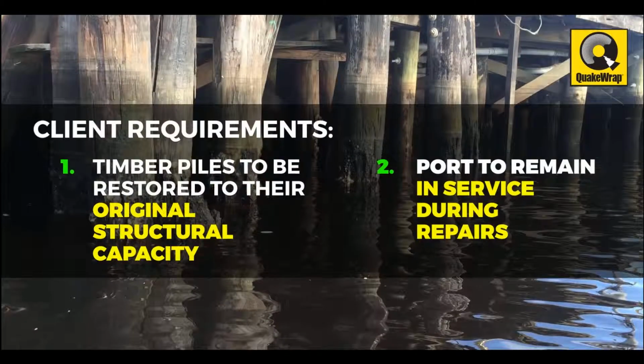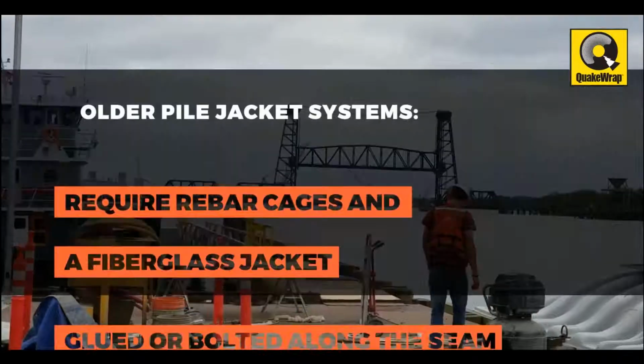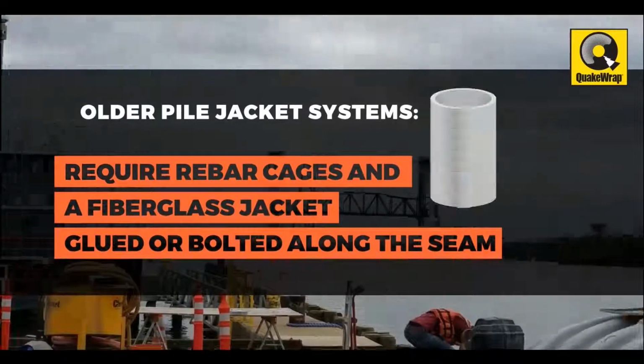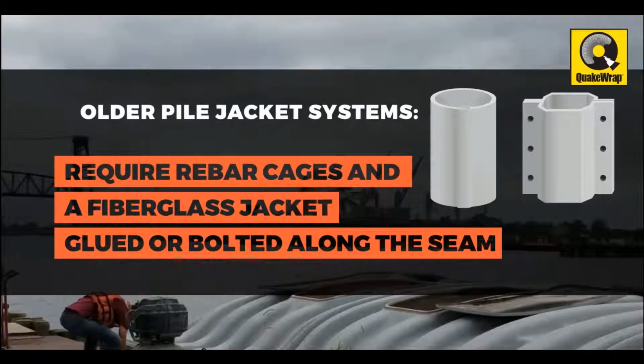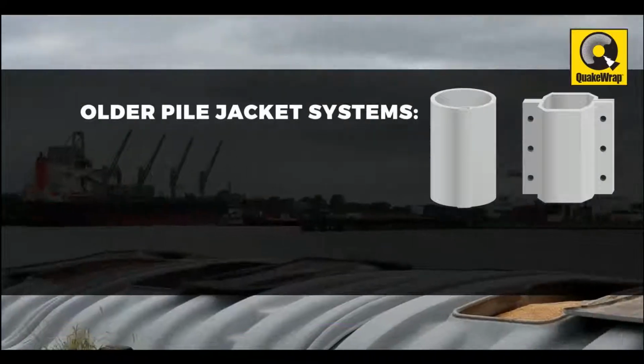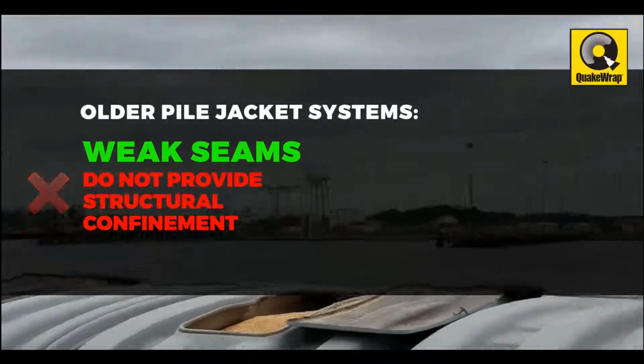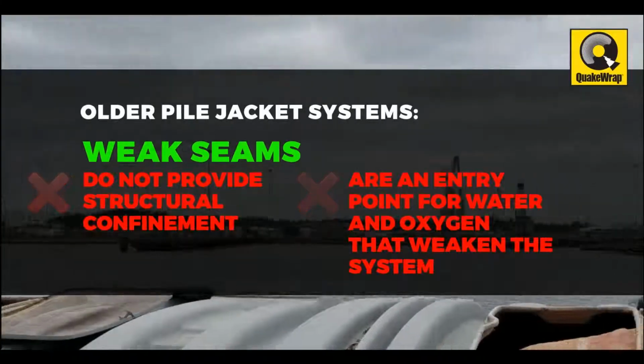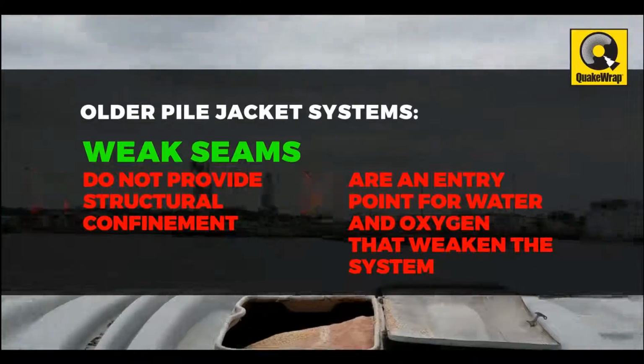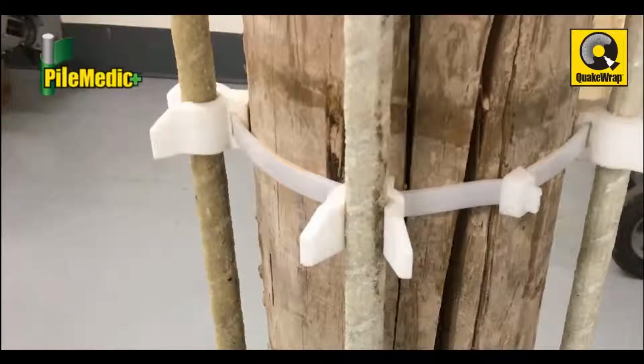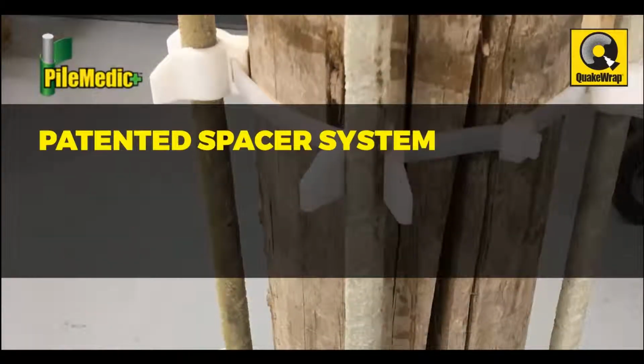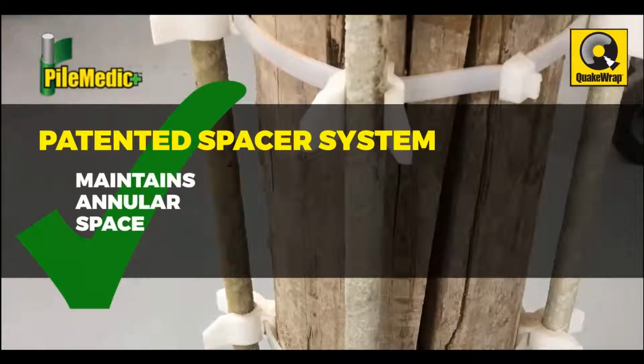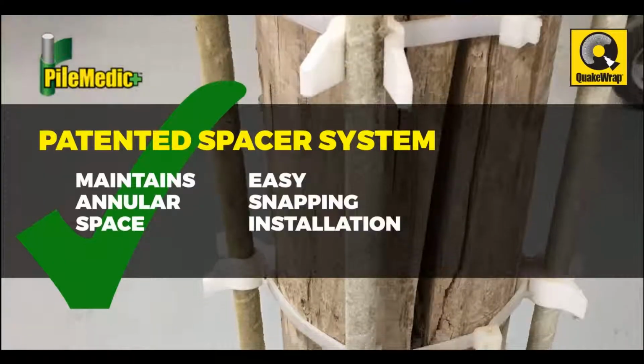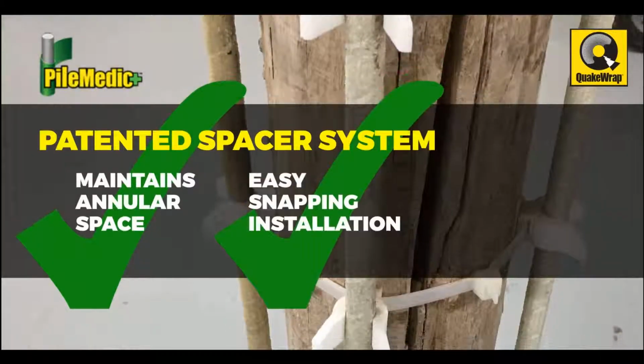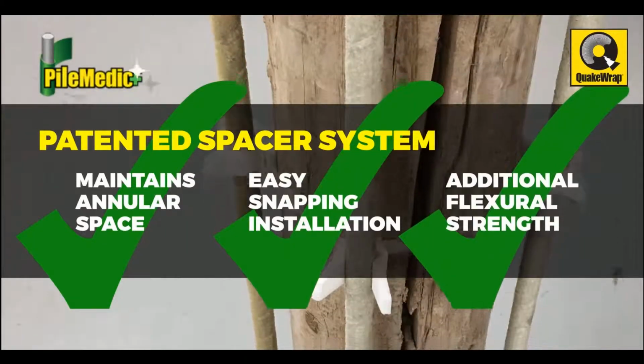port remained in service. Older pile jacket systems require rebar cages and a fiberglass jacket that gets glued or bolted along its vertical seam. These weak seams do not provide structural confinement and are an entry point for water and oxygen to weaken the system over time. The PileMedic system utilized its patented spacer system to maintain the annular space and provide easy snap-in installation of longitudinal FRP rebars for additional flexural strength.